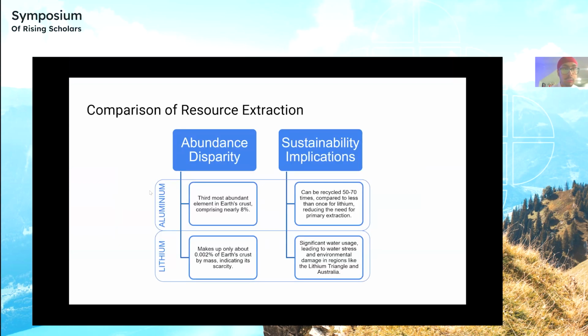All right, resource extraction. Aluminum is the third most abundant element in Earth's crust, comprising nearly 8%. Lithium, on the other hand, only makes up about 0.002% of Earth's crust by mass, indicating its scarcity. Aluminum can be recycled 50 to 70 times, compared to less than once for lithium, reducing the need for primary extraction. Additionally, lithium uses significant water during extraction, which causes stress in regions such as the Lithium Triangle and Australia.